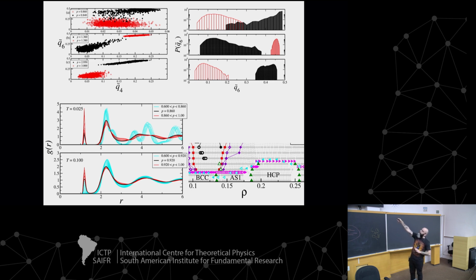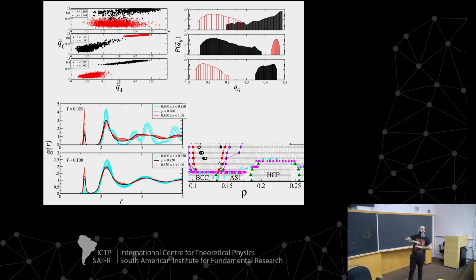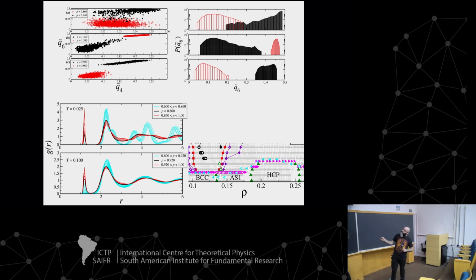If I take the probability of my system having a value of Q6, you can see that one phase is here, another phase is here, and they are pretty well separated. But when I go to the BCC to amorphous solid transition, and I take the pressure at the left of this point and the pressure at the right of this point, you can see that there is some kind of overlap. And if I take the probability, you also have this overlap here.